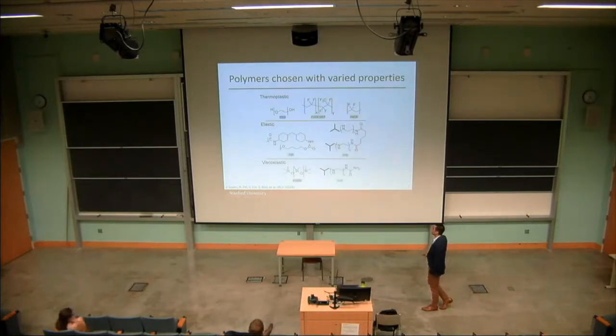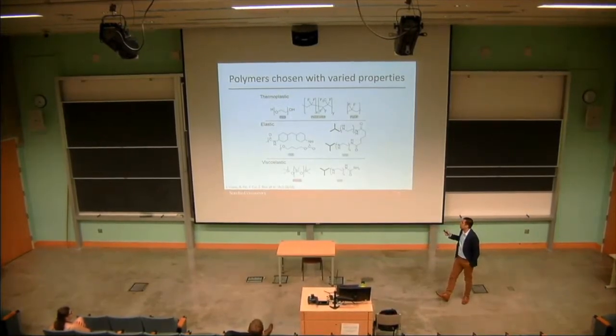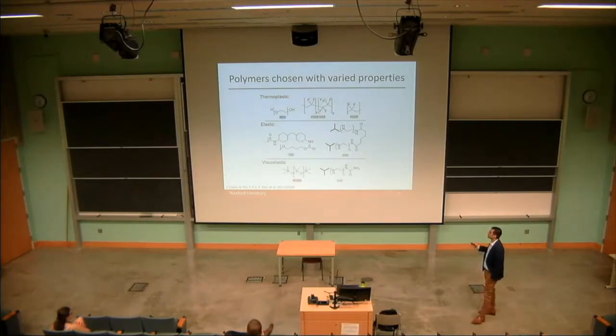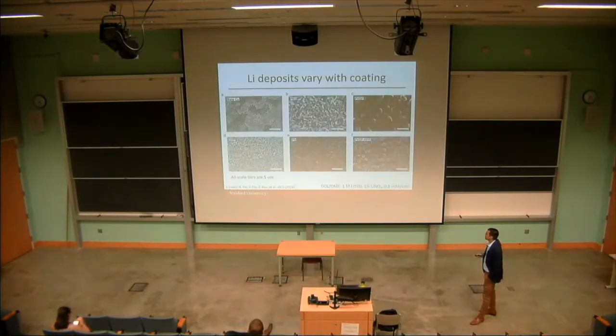And so with that understanding in hand, we can choose a wide variety of polymers from a large set of families that have all been used in batteries. So polyethylene oxide is a common polymer electrolyte material. These fluoropolymers are common binders. Polyurethane is another common electrolyte. Here's our two in-house self-healing materials. And then PDMS has also been used as a coating for the lithium metal and has shown some nice performance. And so when we select all of these, we have very, very different mechanical properties, very different chemistries, really covering a lot of parameter space to try and find what properties of these materials are really affecting the lithium morphology. So we can do the same sort of SEM experiment.